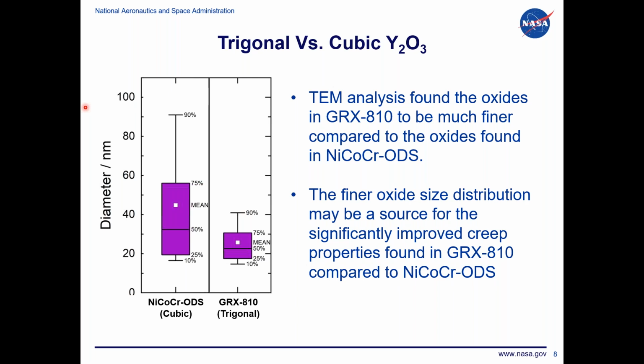For any material science folks out there, what's interesting is the trigonal is actually metastable. And once you free it from the matrix and you characterize it under that electron beam with the microscope, you will actually see it transform back to a cubic during the characterization step, which is really fascinating for us when we're looking at it, but also kind of annoying when you're trying to take pictures. But that right there is just some more of the things that we're starting to discover about GRX-810 that helps it stand apart from other ODS alloys going forward.